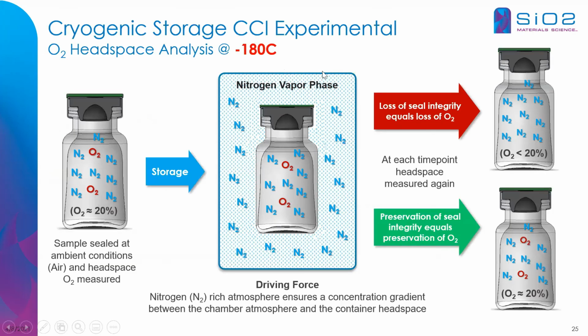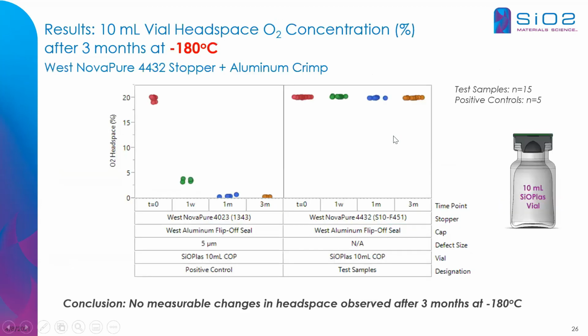For the next study, we're doing an evaluation of CCIT, container closure integrity testing, at -180 degrees C. Here, we use nitrogen gas because carbon dioxide would be a solid at these temperatures. So a very similar test setup, except using nitrogen as the tracer gas. In this case, we've got 3 months of data. On the left side is a positive control.